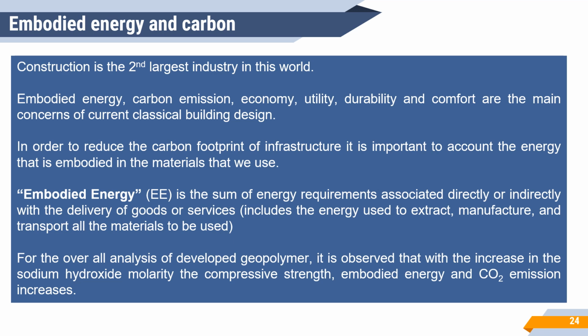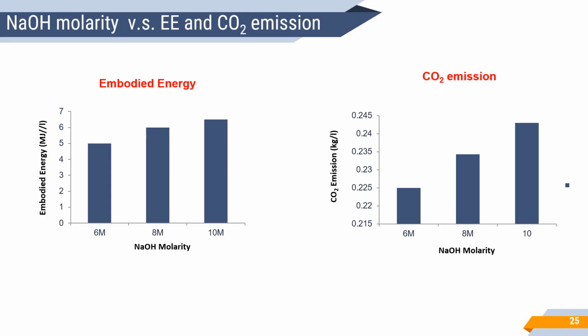For the overall analysis of the developed geopolymer, it is observed that with the increase in the sodium hydroxide molarity, the compressive strength, embodied energy, and carbon dioxide emission increase. A comparative study on the variation of embodied energy and carbon dioxide emission with respect to the increasing concentration of sodium hydroxide in the alkali activator medium is shown here. The dry mix design used was a mixture of fly ash and laterite in a 1:1 weight-weight ratio.